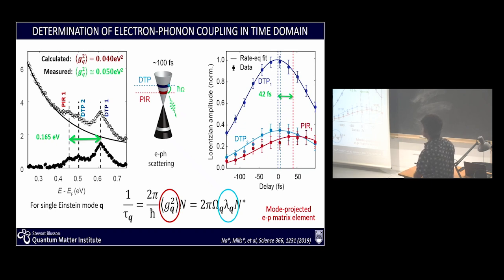And so immediately you can get, from a measurement, a value for the electron-phonon matrix element, really the projected matrix element, and compare that to a DFT calculation here done by Alex Kemper. So that's really the beauty of having enough energy and time resolution and working in the time domain to extract these microscopic quantities.